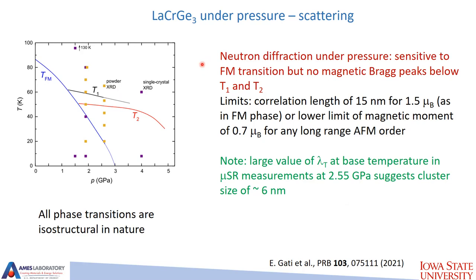Important thing here is that in X-ray, there were no additional peaks. So all phase transitions are isostructural in nature. Now neutron diffraction under pressure, as we saw a few slides before, is very sensitive to ferromagnetic transitions. However, there were no magnetic Bragg peaks seen below T1 or T2.